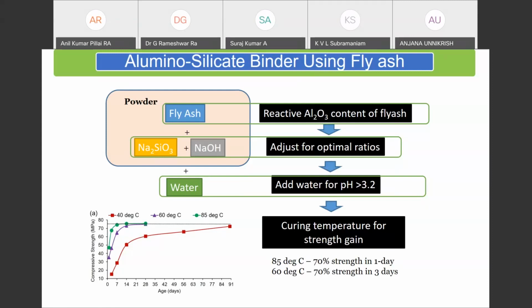It makes it friendlier to use with the use of sodium silicate, and we're able to optimize it, and we are able to produce binders which give us 80 megapascal strength. So this is cement made completely using fly ash, which is activated using sodium hydroxide and sodium silicate. And we're able to hit compressive strengths on the order of about 80 megapascal. And we're also able to bring the processing temperature down to 40 degrees Celsius, which is basically a hot summer day in India. We're able to give a very strong material which can be used for making concrete.